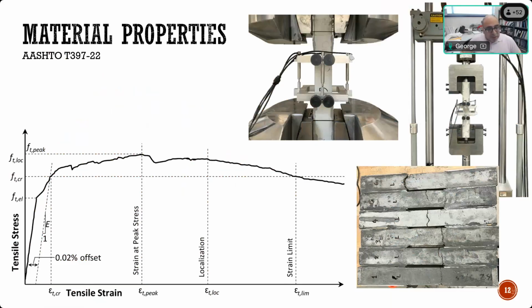So it has to be a strain hardening material to be accepted for use in a bridge component, according to the AASHTO. And you look also at the strain at which the first crack enlarges and becomes localized, like what you see here. These are the localized cracks that you see very big. There are hundreds of very fine cracks, but there is one of them that opens, and that's when the fiber starts to pull out of the concrete. And that's what we label as localization. This is a very important criterion for structural design using UHPC, to know when that happens. If it happens at a certain strain, that's called localization strain. And also we look at the localization stress as well.